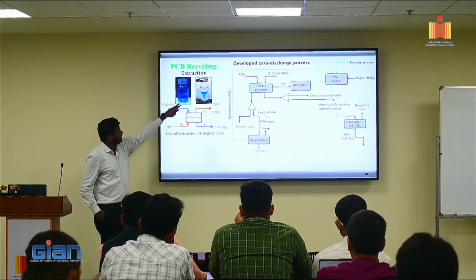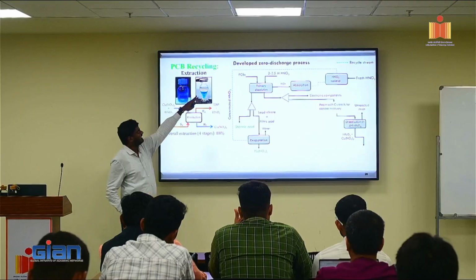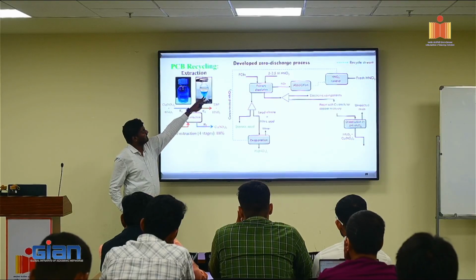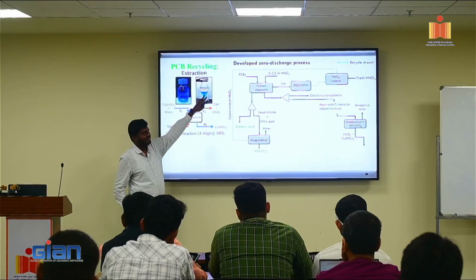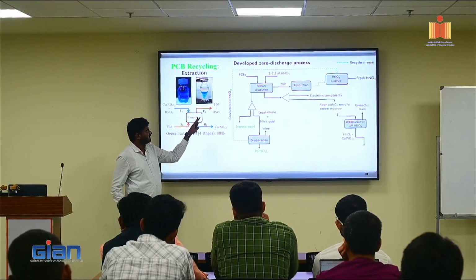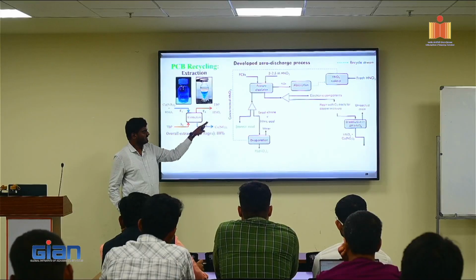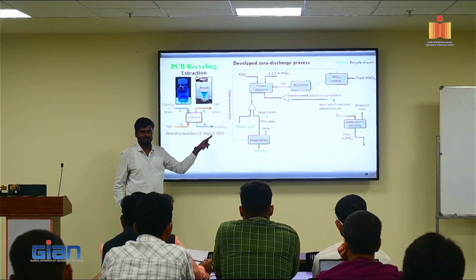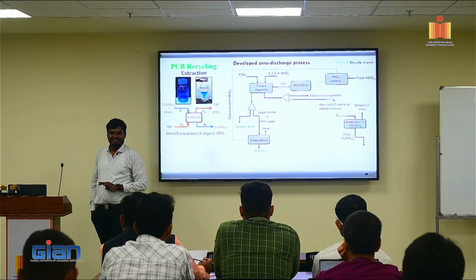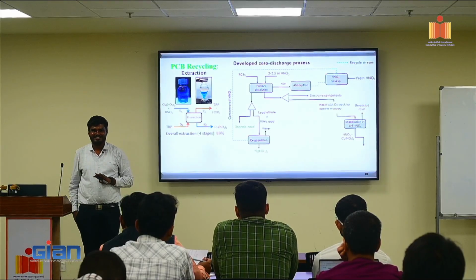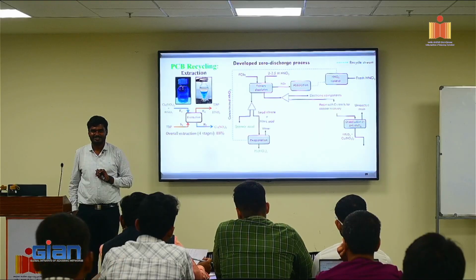So I took this copper nitrate, added tributyl phosphate, mixed and left it in a separating funnel. Whatever nitric acid was there in this blue color solution has transferred to the organic phase. So you get a stream of TBP plus HNO3 and you get another stream of only copper nitrate. But the tributyl phosphate cost was very high. I think 1 liter was around 3,500 rupees.